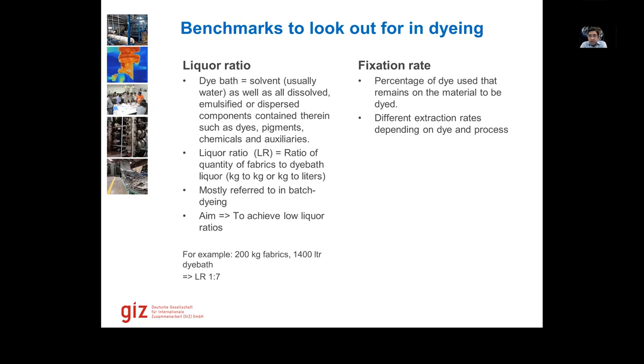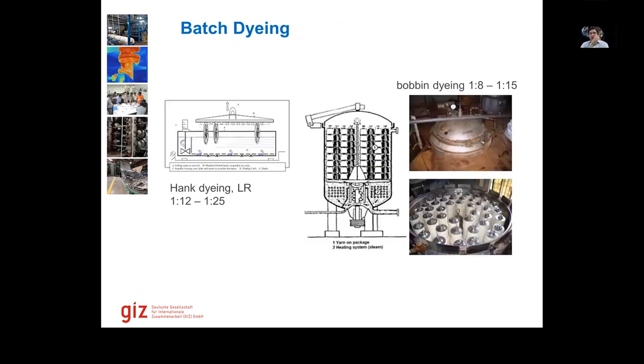And then we come to the fixation rate. That is the percentage of dye used that remains on the material to be dyed. So if we are, for example, feeding in 100 kg of dye, and 70 kg of the dye goes into the wastewater and 30 kg remains on the fabric, then we have a fixation rate of 30%. And different extraction or fixation rates are there depending on what kind of process we are using, how much heat we are using, and different kinds of chemicals or dyes that are being used. So fixation rates vary. So we have different kinds of batch dyeing machines.